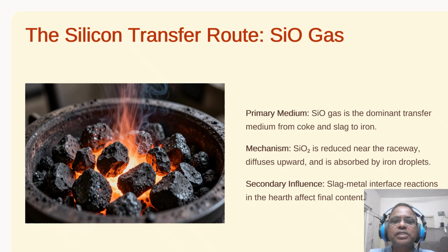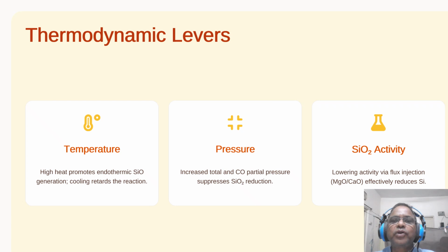So coming to discuss the next slide about our thermodynamic levers. If we want to stop that silicon sneaking in, we have to pull three main levers. Look at these icons: a thermometer, a pressure gauge, and a flask. First, temperature. High heat is like fuel for silicon gas. Keep it cooler and the reaction slows down. Second is the pressure. If we crank up the pressure inside the furnace, it literally squashes the gas production, keeping the silicon trapped in the slag.